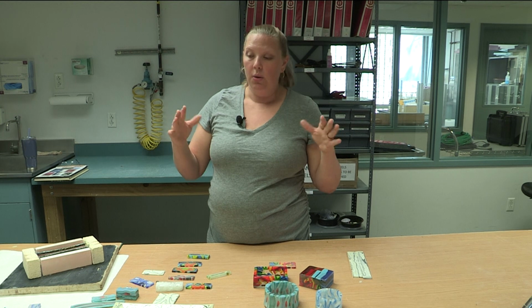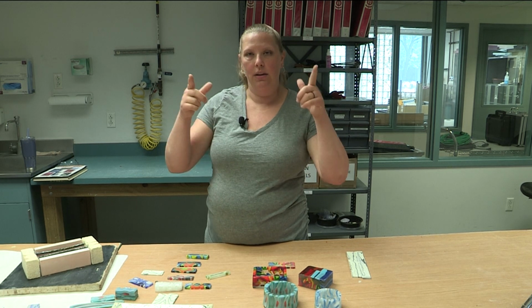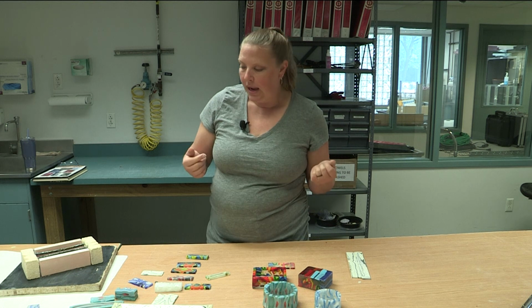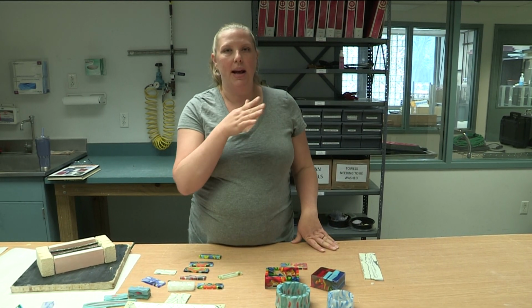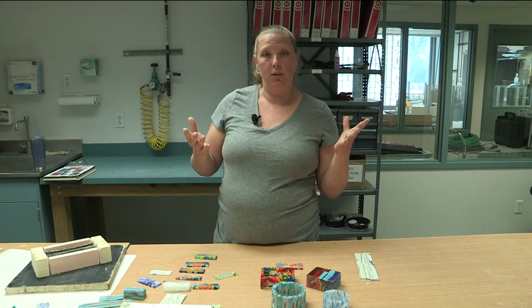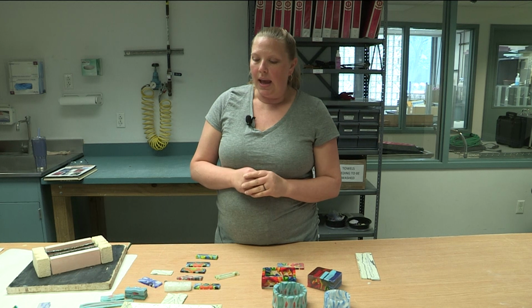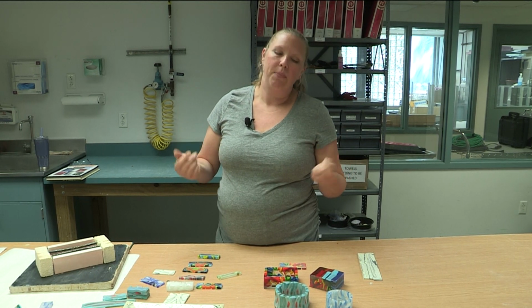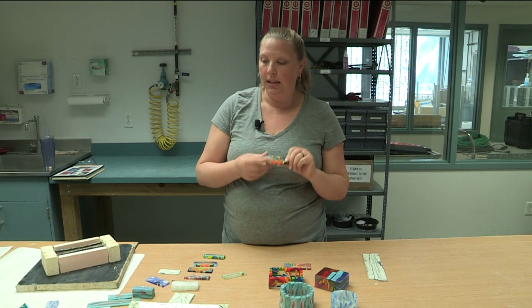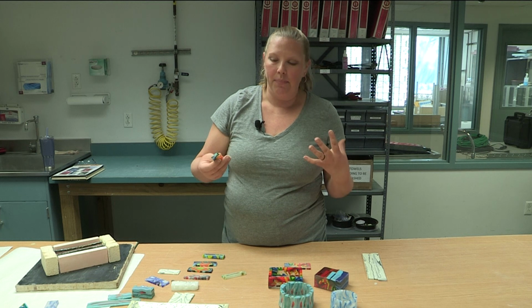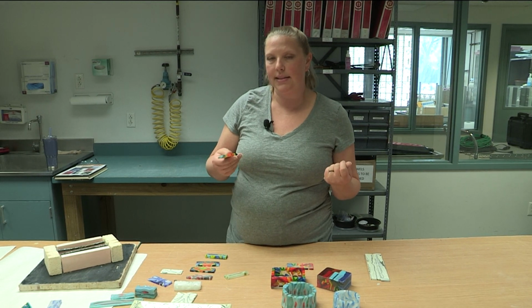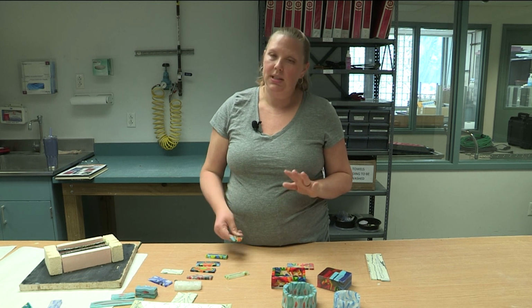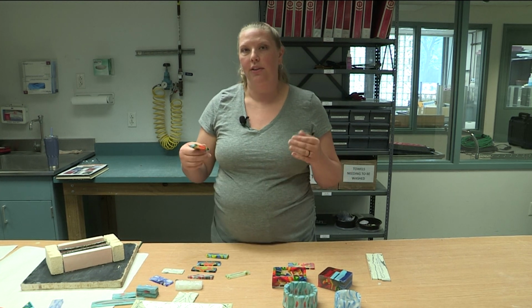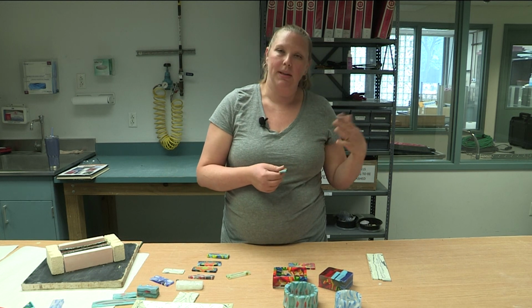We call that a full fuse when we take all of our pieces, melt them together into one smooth, nice flat piece of glass. And then that will get cooled down, taken out of the kiln. And then we place that on a mold, and then it gets slumped, where it actually takes the form of a mold, or in this case, to make a dish shape. And so it has to go through the whole series of steps. So unfortunately, you can't take your Murrini and just put it in the mold, because there are different temperatures that the glass has to go to. When you slump the glass, it has to be at a much lower temperature than full fusing the glass. Unfortunately, you have to go through the full fuse first, and then you have to go through the slump second.